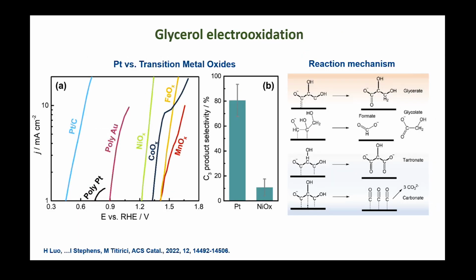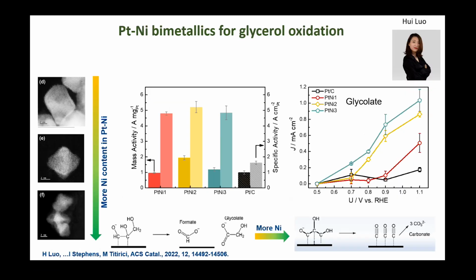So we've started looking at glycerol oxidation, and we've started looking at the fundamentals of the reaction mechanism on platinum carbon, and also on more non-critical elements. But of course, you can't have everything in life. The more you get to non-critical elements, the higher the potential at which glycerol oxidation happens, and the selectivity to C3 products, which is something that we would like, decreases quite a lot compared to platinum. But saying that, platinum is also very easily poisoned in these reactions.